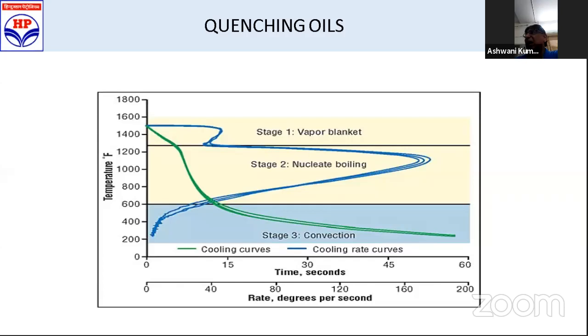After that, with further cooling, the vapor blanket collapses, and then we get into nucleate boiling. As you can see on the graph, the nucleate boiling starts. This is the fastest heat transfer region. Then the rate of heat transfer is dependent on the oil's overall molecular composition. And after this, when the temperature at the hot oil and steel interface falls below the oil's boiling point, nucleate boiling ceases and you get into convective cooling. Heat transfer is now dependent on the oil's viscosity. As I said, heat transfer rates increase with lower viscosities and decrease with increasing viscosity. So viscosity plays an extremely important role.